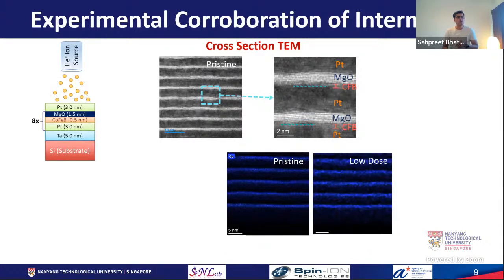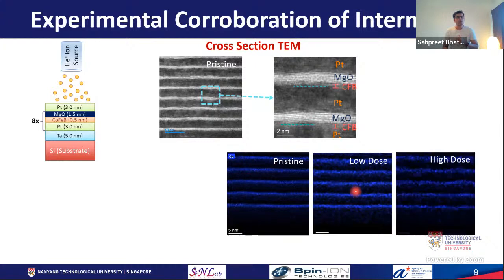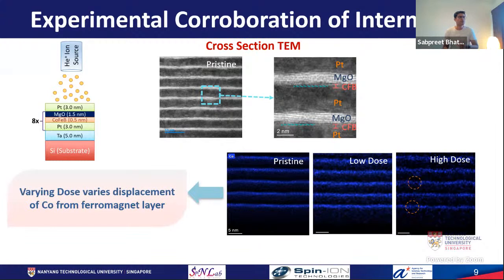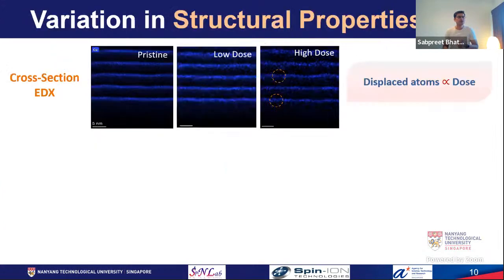On a very low dose, you can see that between 2 adjacent cobalt layers, there are cobalt atoms displaced after the irradiation. On a 4 times higher dose, you can see that the displacement of the cobalt atoms even from the ferromagnetic layer has increased. So from here, we can infer that by varying the dose, the cobalt displacement is varying. And to further understand, we have also carried out other measurements. Because of the time constraint, I'm not going to show that.